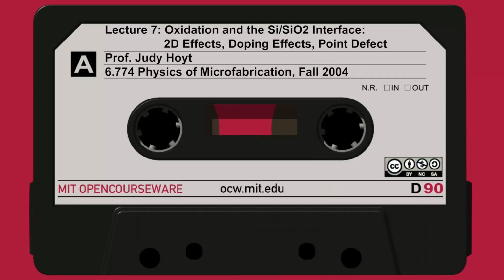And by the way, this buried layer can be 2, 3, 4 microns away. It doesn't have to be close. The interstitials diffuse very quickly and very rapidly. So this is the problem. Oxidation can have effects at a distance, a micron or so away, that can greatly impact what's going on in the chip. So they diffuse away from the interface, and they enhance the boron diffusion rate.